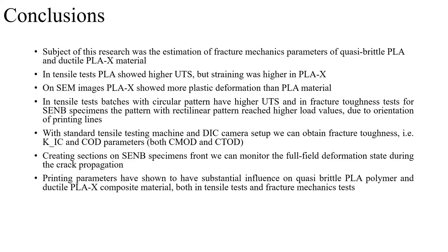In the continuation, the fracture toughness tests were done, and I've also mentioned the conclusions for both materials. The fracture toughness results were attained using a tensile test machine with a 3-point bending test fixture and, with the addition of a DIC camera device, we could also attain the COD parameters, which proved useful for the ductile material, which couldn't hold the plane strain criterion. Also, we've shown you some SEM microscopy images showing the fracture surfaces of both materials and how they differ.